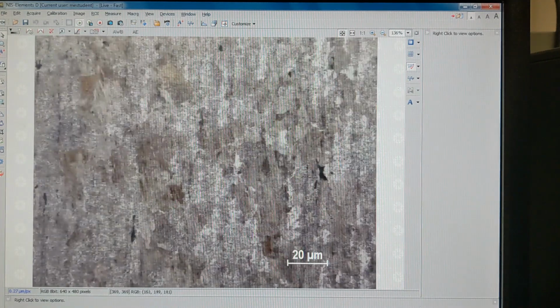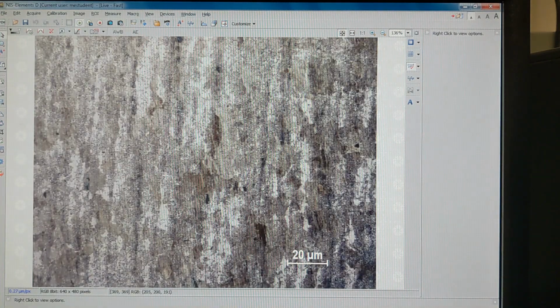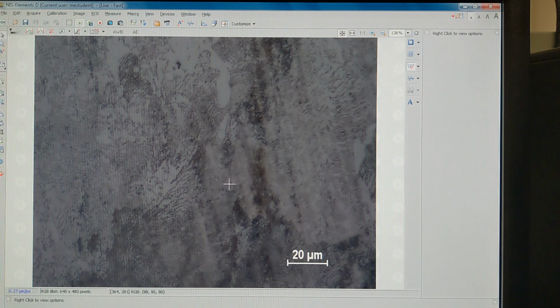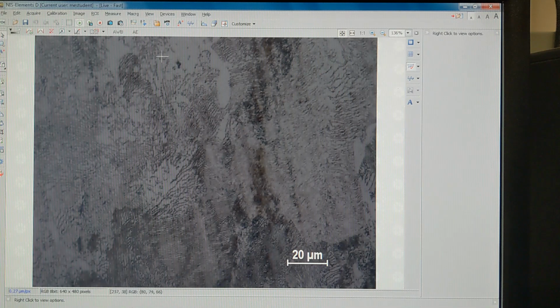So our grains, when this was formed, were drawn through a die, and that die forces our material to go in a certain direction. This is a little bit easier to see if you follow the path, it goes down like this, which is the direction of drawing. And again, if we zoom in, this is 20 times, this is 50 times again. If we zoom in, we again see our pearlite layers here, and our ferrite.